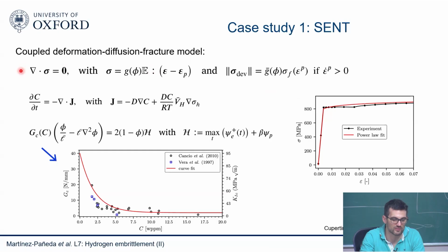So it's an elastoplastic phase field fracture model with hydrogen. So you have an equation for the transport of hydrogen, you have a stress-strain behavior. So we did a uniaxial tension test. We fitted that. We have a driving force that is 10% of the plastic work plus the elastic work. And the toughness degradation with hydrogen, in this case, we have a lot of data from the literature for this material, so we just fitted the data from the literature. We didn't take the atomistic approach, so to say.